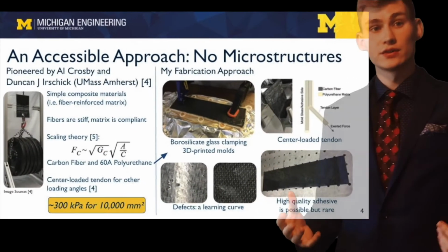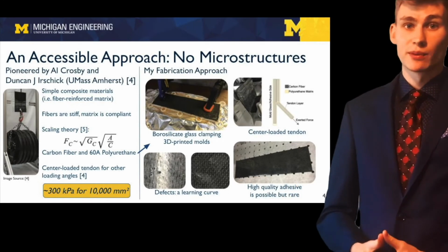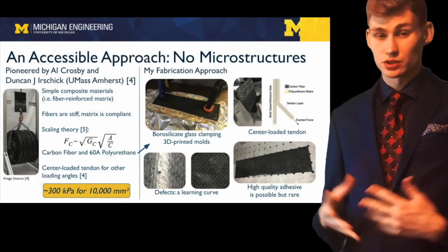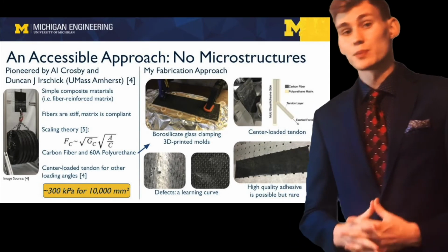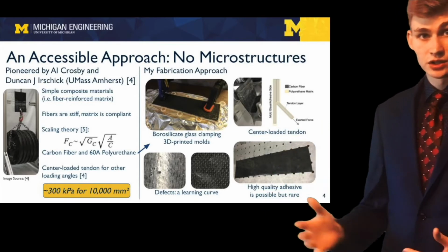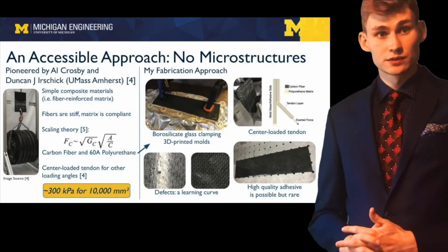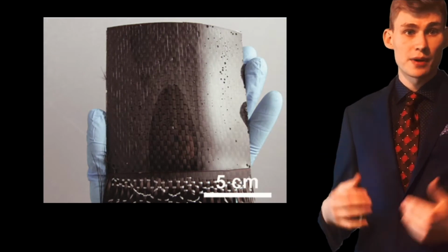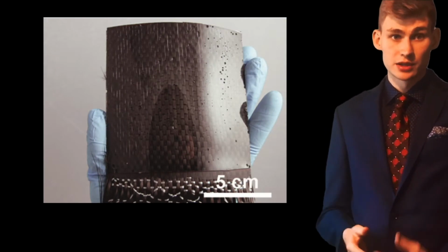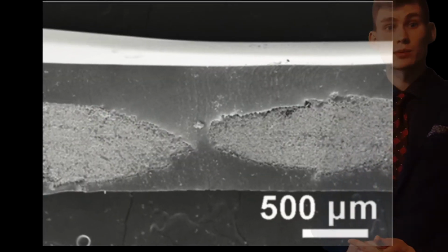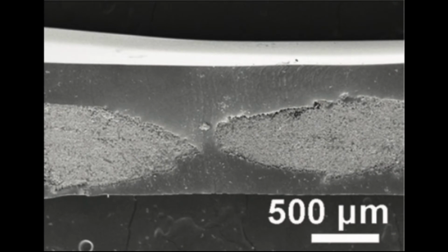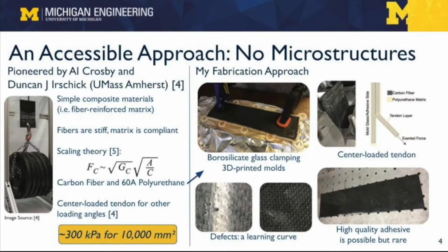Now let's take a look at a different approach, one that is much more accessible because it does not require microstructures, which are difficult to fabricate. This approach was pioneered by Al Crosby and Duncan Irschick at UMass Amherst. They utilized compliant composites consisting of a compliant matrix reinforced by stiff fibers. The compliant matrix serves to increase the compliance perpendicular to the surface, which essentially helps the adhesive pad conform to surfaces, acting just as the setae would to maximize the molecular contact area.